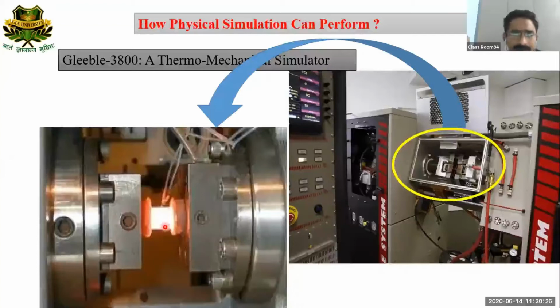Another welding unit is there with the Gleeble system. So at the start of the experiment, we usually weld these two thermocouples to the sample. Then we start our hot compression test. With the help of these two thermocouples, we can capture the real-time temperature of the sample. So really, it's an appreciable machine which has a versatile capacity to do various kinds of experiments.